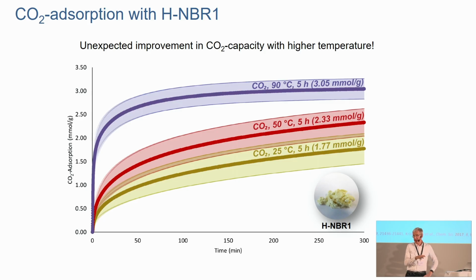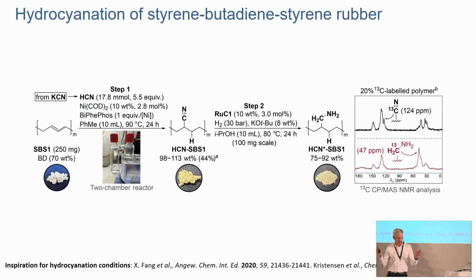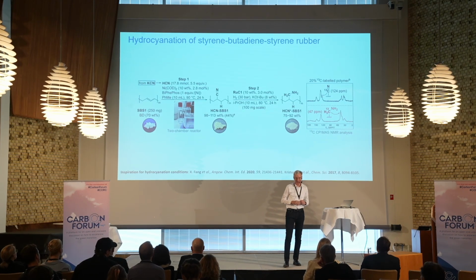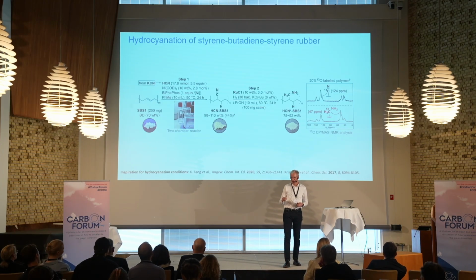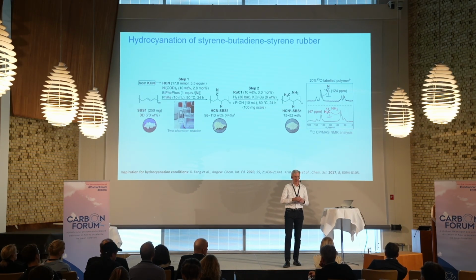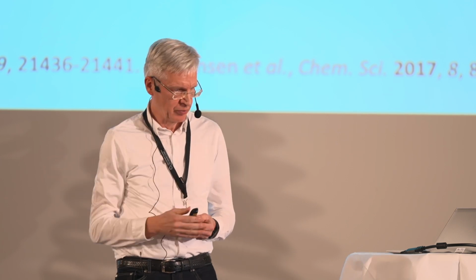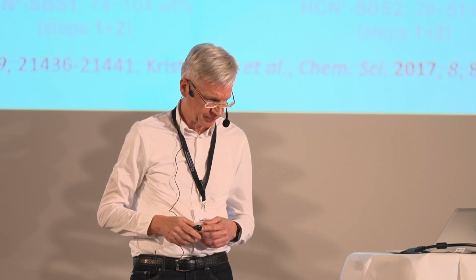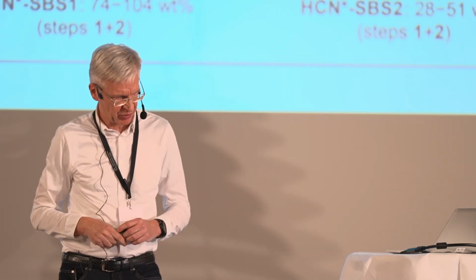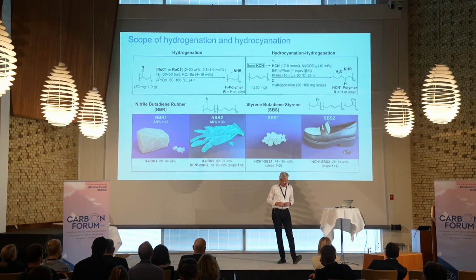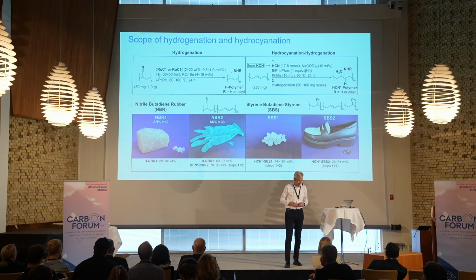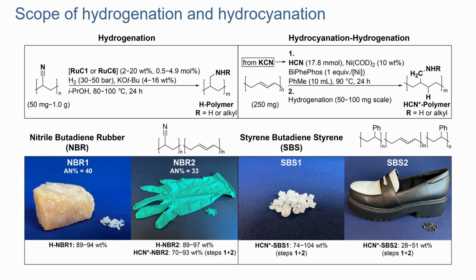This is an example of styrene butadiene rubber, which has no nitrile, so it has no nitrogen. But again, we can do some funky chemical reactions and introduce this nitrogen, which I won't go into too much detail, but just to say that it works. And we can even do it with a nitrile butadiene rubber. So Simon's done some really nice work with that, introducing more nitrogen because we have this butadiene in there. That's shown in the examples behind me. These are some of the examples that we've used. There are the chemical processes that we've made nitrile butadiene rubber, both with just adding hydrogen, but also adding hydrogen cyanide and then reducing to increase the nitrogen content.